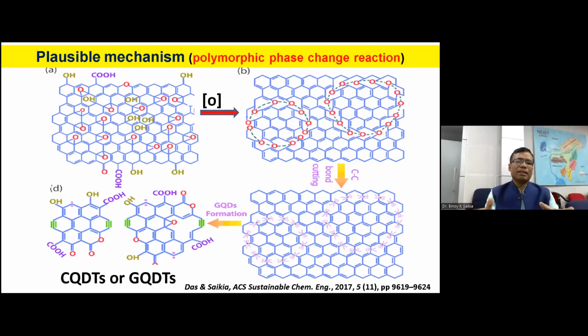Let me explain: coal has aliphatic and aromatic components, and particularly in this subbituminous rank, and in most coal, more than 75% of the carbon is aromatically bound. In our case, it is about 74% aromatic carbon. When applying oxidation in the presence of ultrasonic energy, we used an oxidizing agent, and in the presence of oxygen it gets oxidized. At the same time, this is a polymorphic type of reaction in which bond breaking and bond formation lead to the formation of graphene quantum dots or carbon quantum dots.